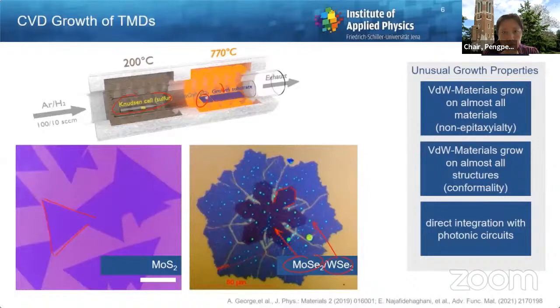These materials are all van der Waals materials, which means out of plane, they only bind very, very weakly. And this has a profound impact on growth, namely that they will grow on almost all materials, irrespective of their epitaxial compatibility. In this case, the growth is on silicon dioxide, which is of course not crystalline at all, but you still observe these crystalline growth modes.